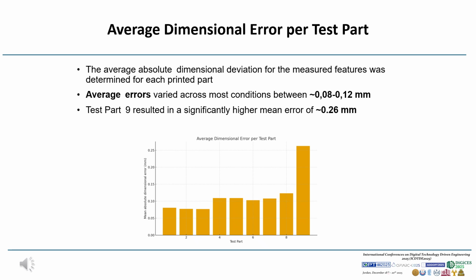This slide shows the mean absolute dimensional error for each of the 9 test parts, averaged over all measured dimensions. Most parameter combinations produce errors of about 0.08 to 0.12 millimeters, which corresponds roughly to 1% for a 10 millimeter feature. However, one combination, test part 9, clearly stands out with a much higher error of about 0.26 millimeters, and this is our worst case.